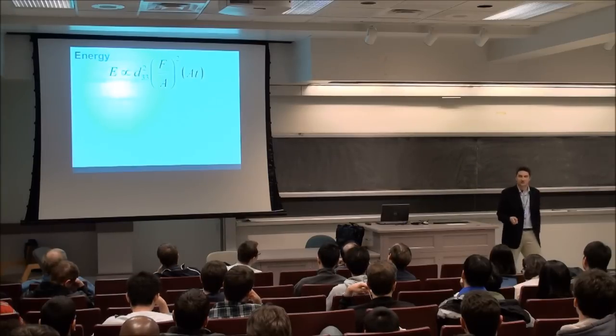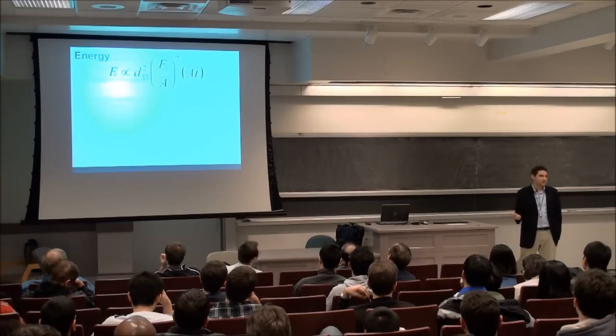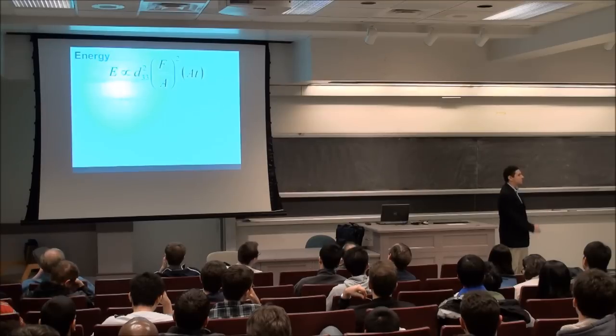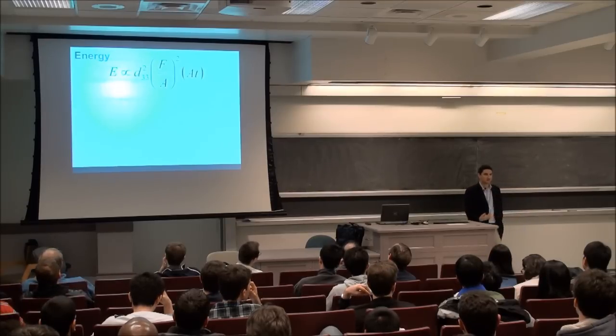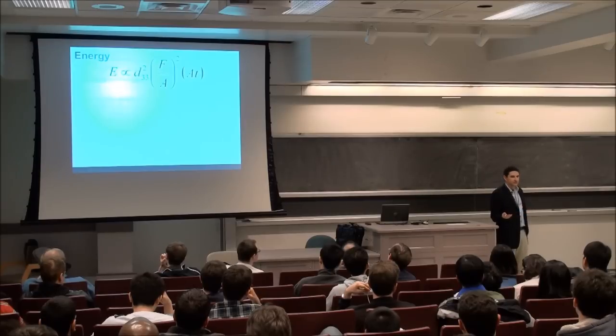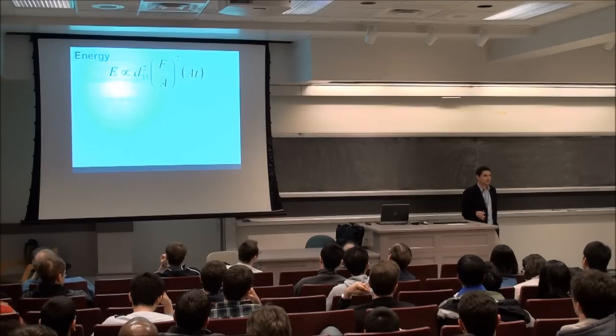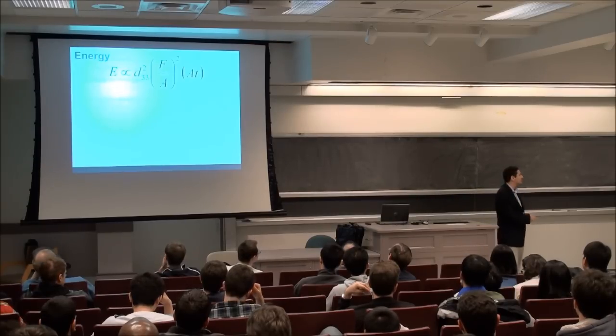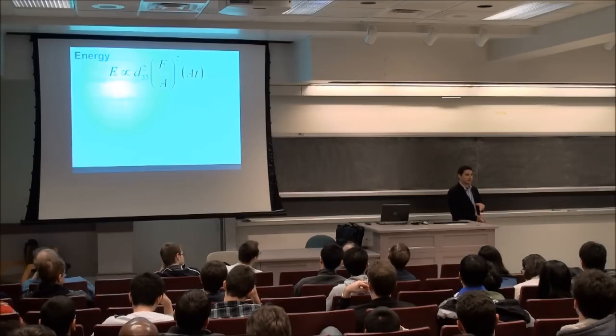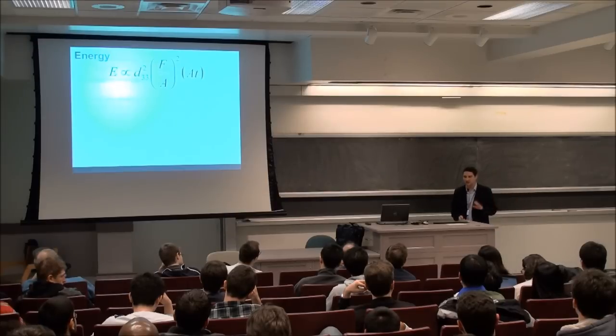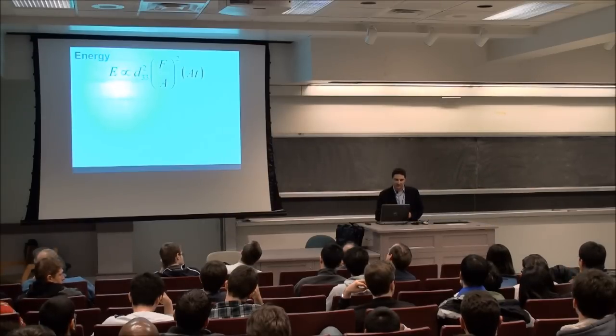Okay, that's one part of the equation. The second thing is the applied stress, this F over A term here. So the harder you stress these materials, the more power they're going to be able to generate. So neither of those tells you much about material selection. The thing that matters in material selection is this d constant here, this piezoelectric charge constant, which is intrinsic to the material and gives you a parameter that tells you how efficiently you can convert energy in these materials.